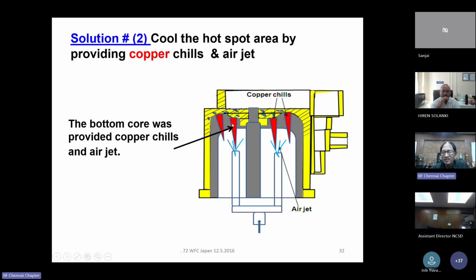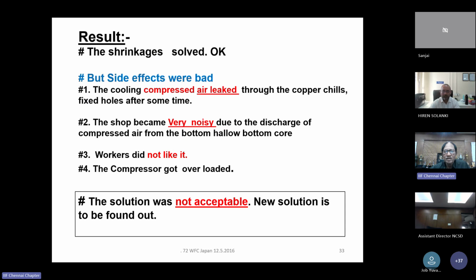We drilled and made all the pins with a lot of difficulties and blow compressed air for cooling this, so that the core temperature has come down from 400 to around 250 to 260 somewhere. Then we poured some castings and found that no shrinkages, no leakages, no problem at all. But the problem is different. But the side effects are very bad.